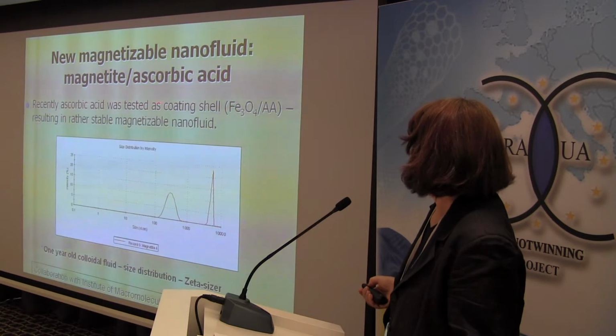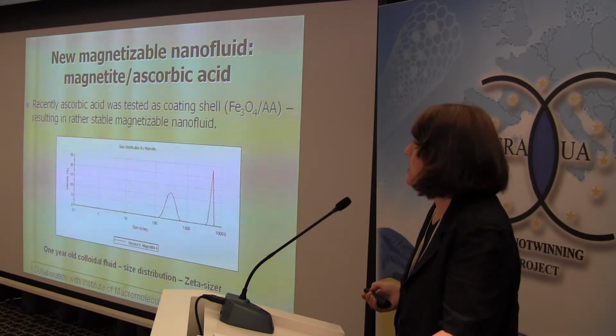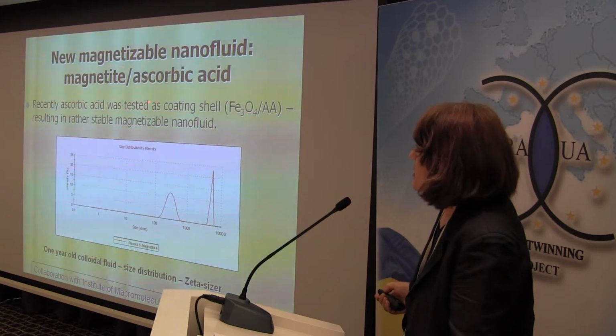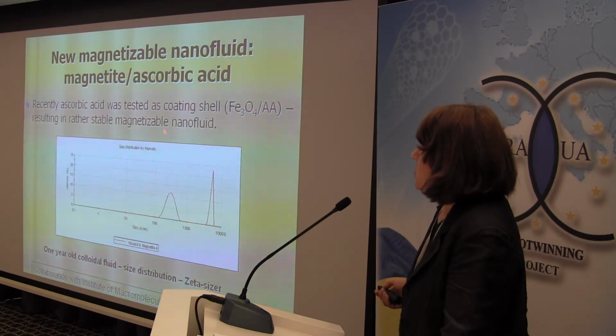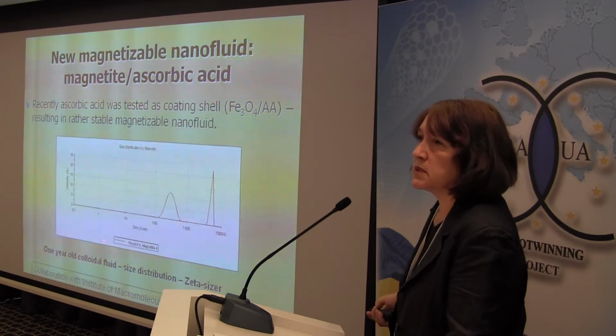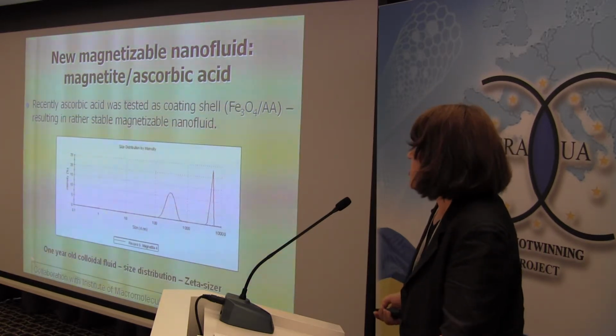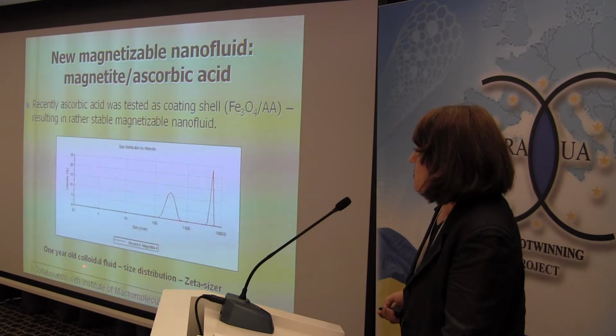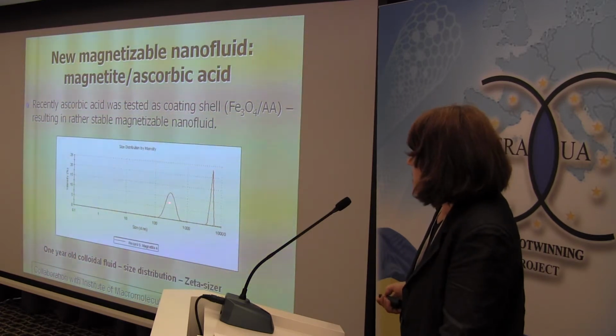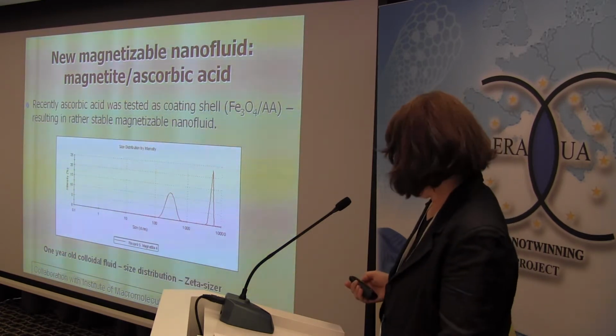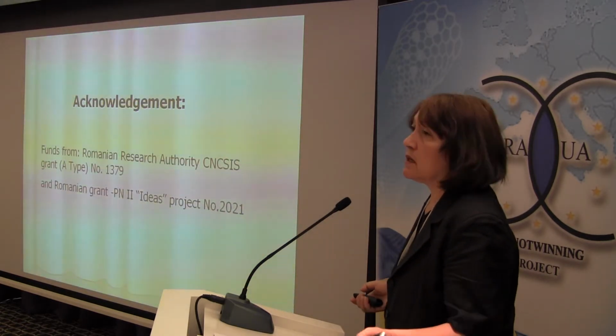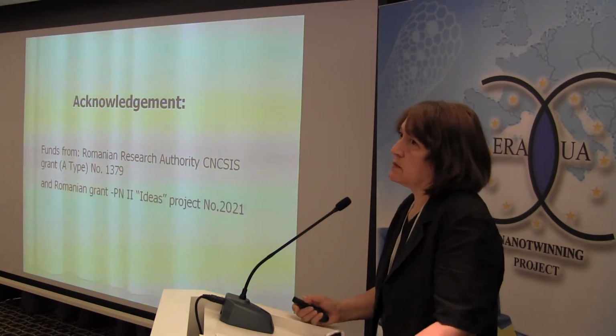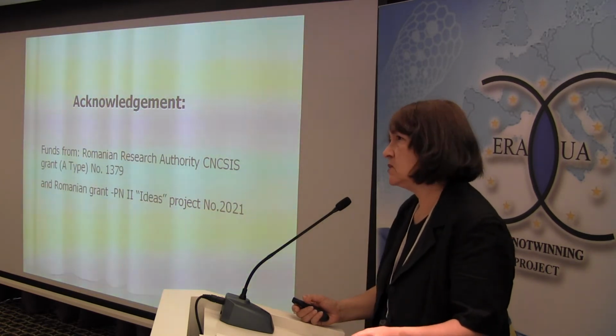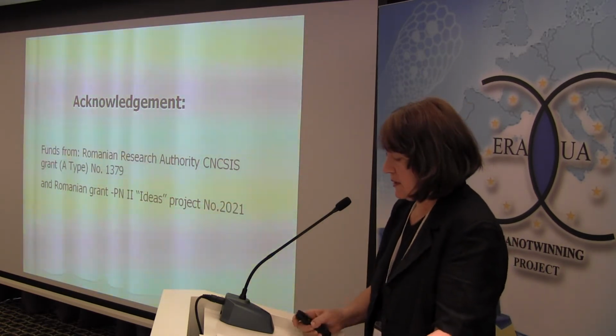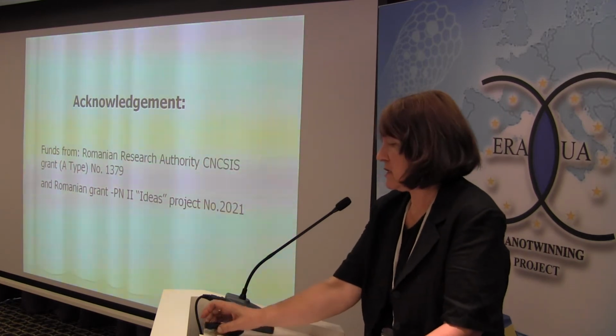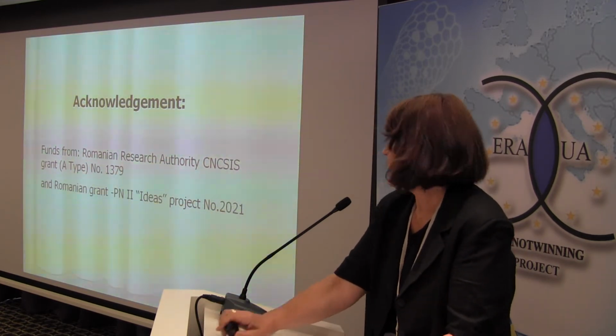And finally, the new fluid that we are going to study next with ascorbic acid, and with the new investigation method, the zeta potential measurements. It is after 1 year, and it is still stable in some respects. I need to say that generally those fluids in water are stable, at least in our case, for a few months, while the other ones, based on hydrocarbons, were stable for some years. Thank you very much.